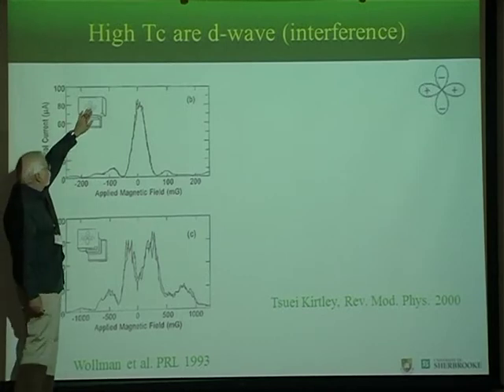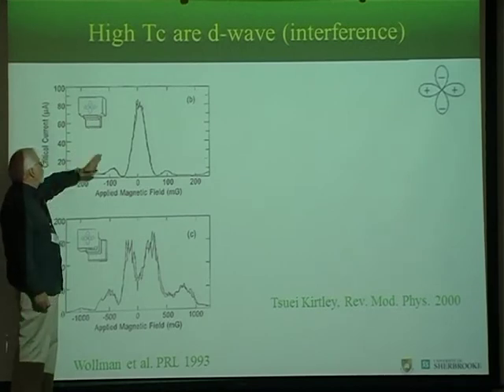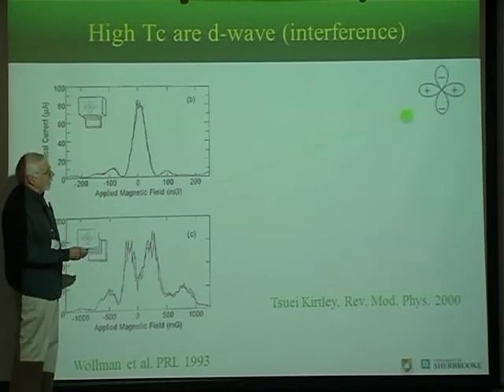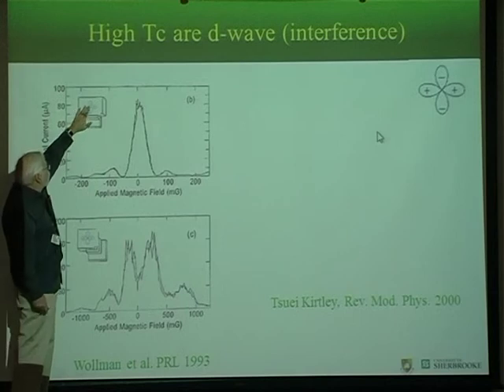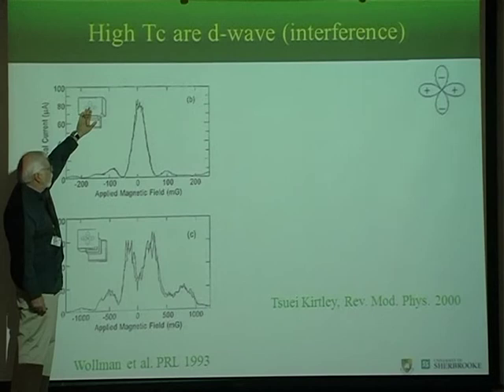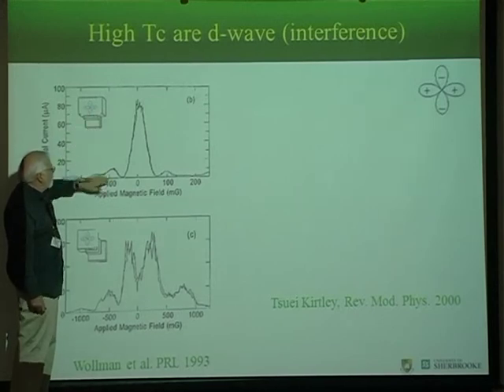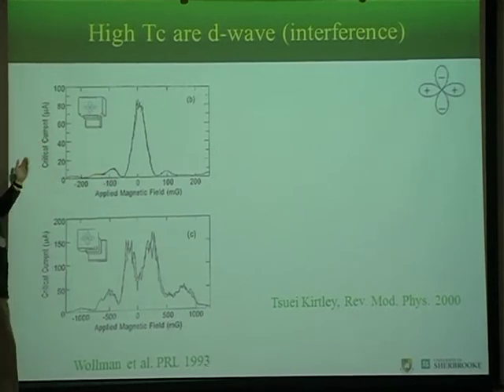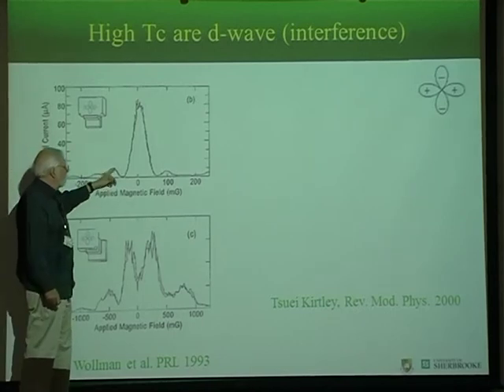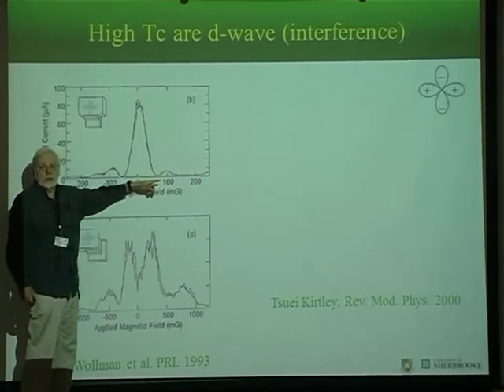So you look at the Josephson junction. Okay, if you're not familiar with this, don't worry. The only thing you need to know is that it's D wave. So here is just a single ordinary Josephson junction between an S wave and a D wave superconductor. And if you look at the magnetic field dependence of the critical current, it should look like a Fraunhofer diffraction pattern. So this is what you see.